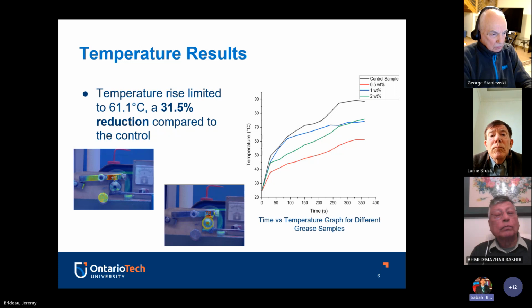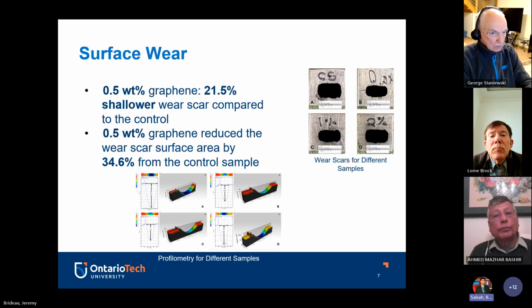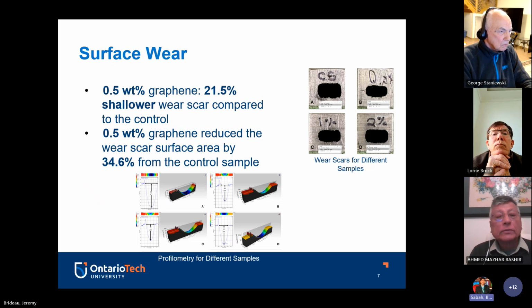And then once we've collected all these temperature results, we actually can use that cube that we had and get the wear diameter, wear scar area, and also the depth of the wear scar. So as you can see probably from these photos, I'm not sure if it's clear and obvious, but the 0.5 sample has the smallest area of any of the wear scars, which was actually 21.5% shallower than the other ones.